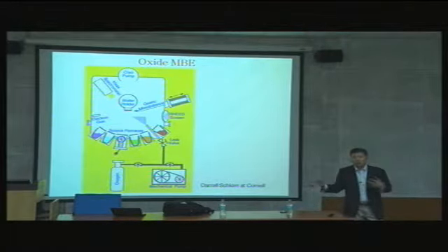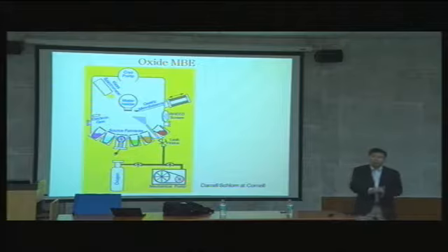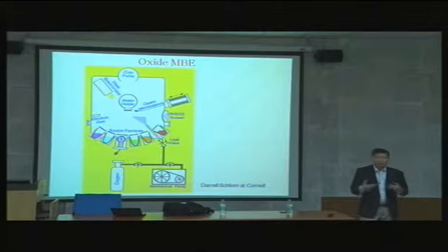week. Because when you grow strontium titanate on silicon, the silicon immediately oxidizes, forming an amorphous SiO2 layer. So in order to overcome this, you have to use a strontium layer first. If titanium goes first, then titanium silicide forms, which is not ideal. So what kind of element do you touch first? That's the way you have more degrees of freedom to play with.